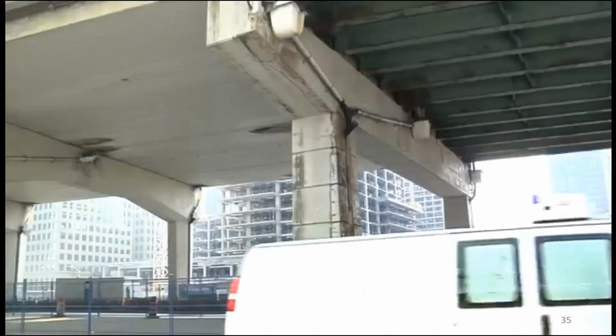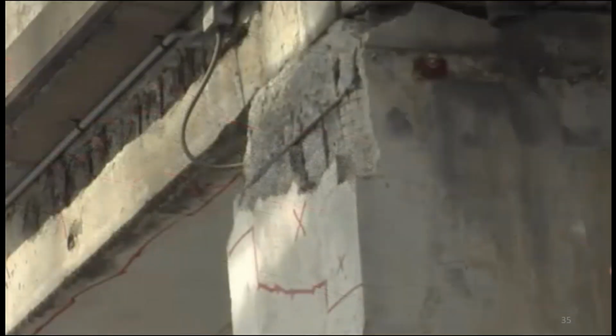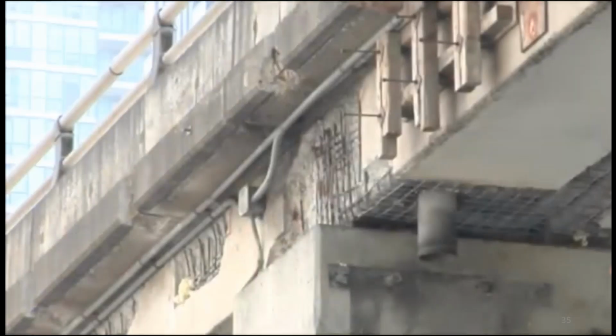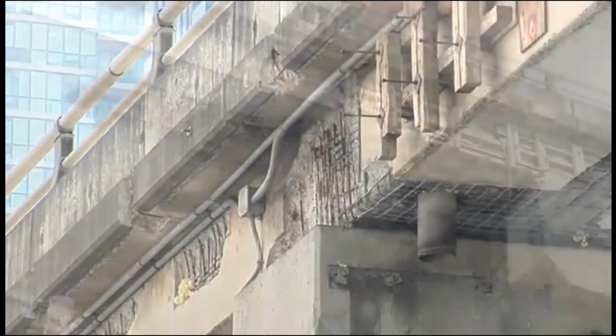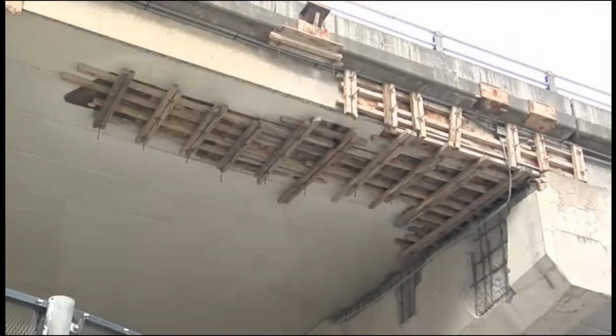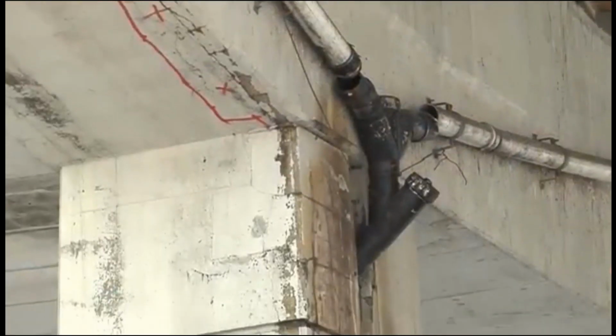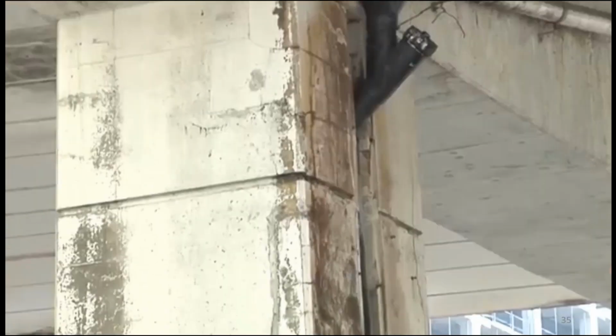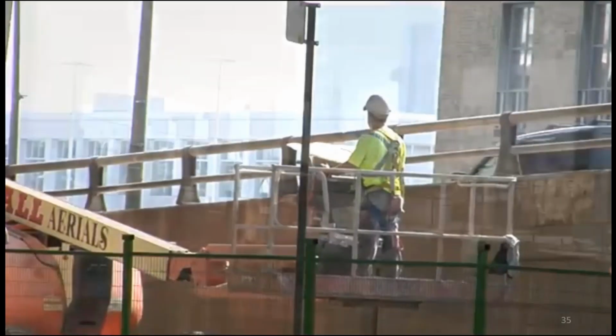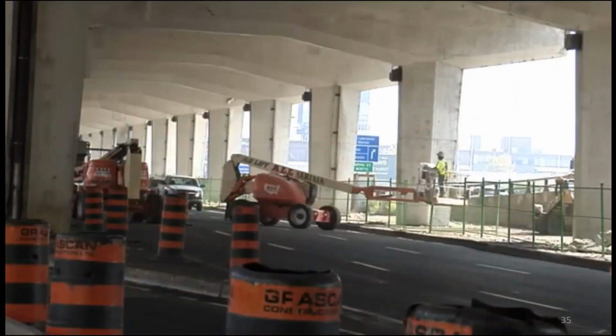However, as the structure ages, the bond between the surface layer of concrete and its reinforcing steel breaks down. As a result, incidents of loose concrete falling from the structure have increased in recent years. And it's important to know that while the city is addressing this issue with proactive measures, such as removing the loose concrete and regular inspections, the expressway is structurally sound.